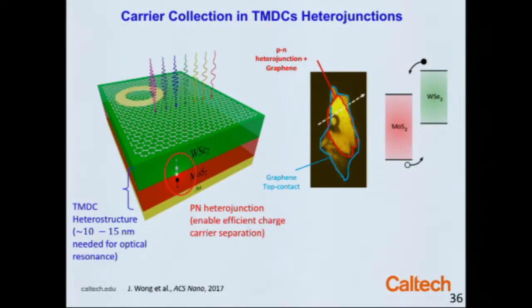So then let's try to make a solar cell, by making a junction between two semiconductors. Tungsten diselenide is known to be native p-type, we think due to tungsten vacancies in the structure that render it p-type. Molybdenum disulfide is known to be native n-type, probably due to sulfur vacancies in the basal plane, which act as donors. This forms a type 2 PN heterojunction.